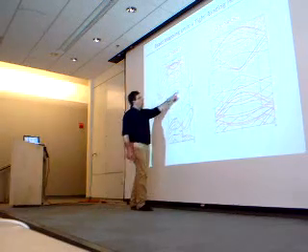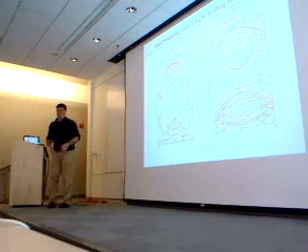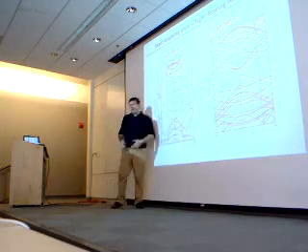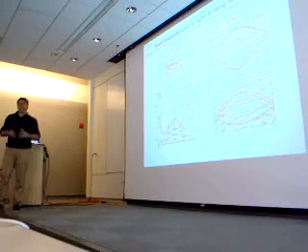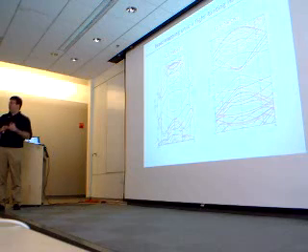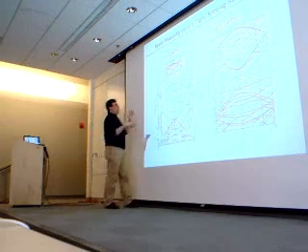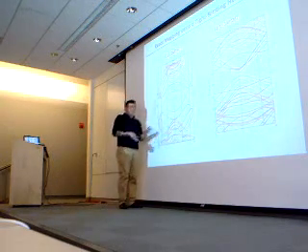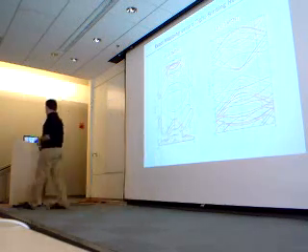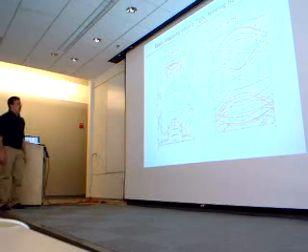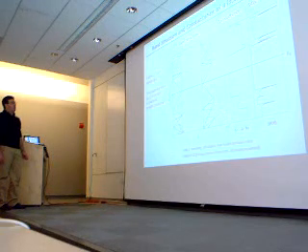To do the PWSCF calculation, the red points, we used thousands and thousands of plane wave basis functions. While to do the Wannier interpolation, we are diagonalizing onto a basis that is just 2.5 Wannier functions per every carbon atom. So every 2 carbon atoms, there are only 5 Wannier functions. So this is really the smallest possible basis set in existence that on top gives you a perfect band structure. That's why they are so good to construct the electronic structure of nanostructures. And if I go back, this was the example I wanted to describe.